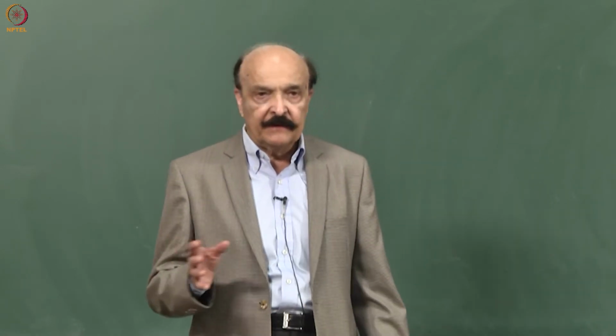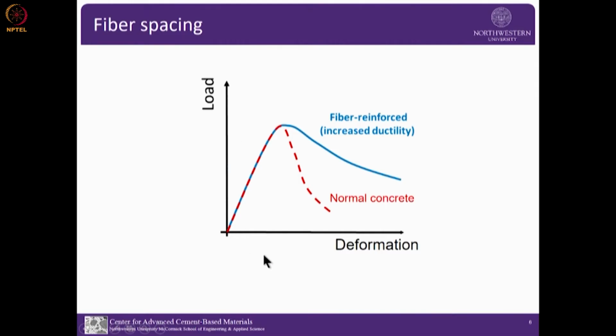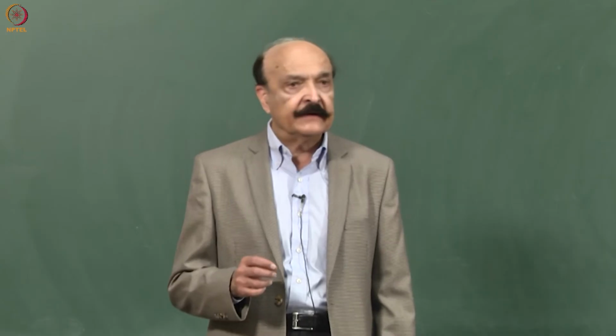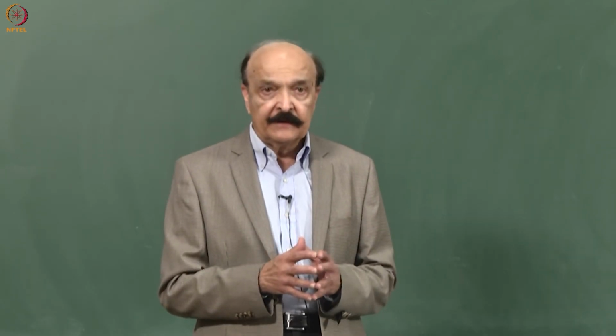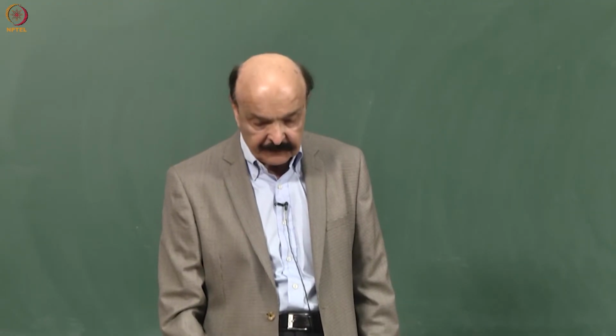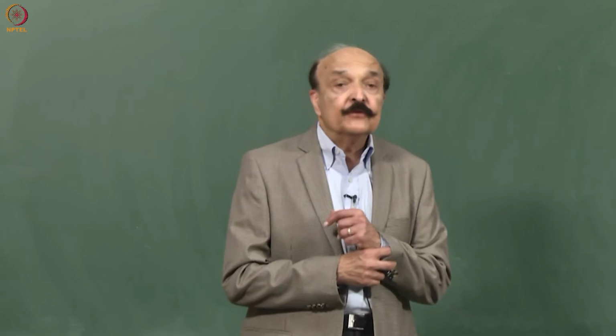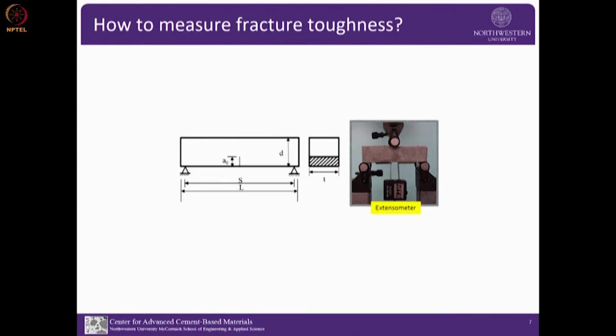If you look at fiber reinforced concrete, whether in tension or compression, load versus deformation, we know that normal concrete in compression or tension is characterized by strain softening, very important especially in compression, and in tension. When we have fibers, and I am talking about a percent, it would not change the modulus. It generally does not change tensile strength, but it does change the post-peak substantially. So crack control is the main reason we are now using macro fibers in conventional fiber reinforced concrete. The toughness becomes important. So how to measure fracture toughness?